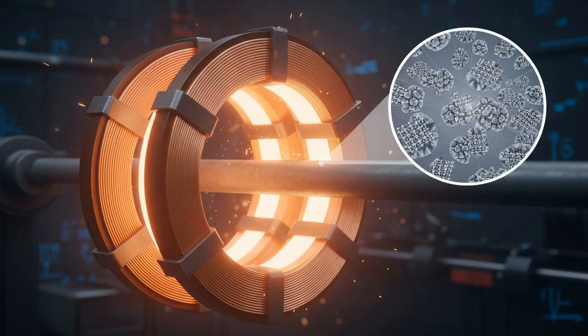Printed superalloys often have a fine-grained structure, which is great for strength but bad for high-temperature creep. This is where MIT's directional recrystallization comes in. This is a post-print heat treatment that acts like a magic wand for microstructure. A 3D printed rod is passed through an induction coil at a very precise speed and temperature. This thermal gradient sweeps through the material, causing the chaotic, mangled spaghetti of fine grains to snap into alignment, forming massive, single crystal-like grains. This technique could allow 3D printed blades to finally match the creep performance of single crystal